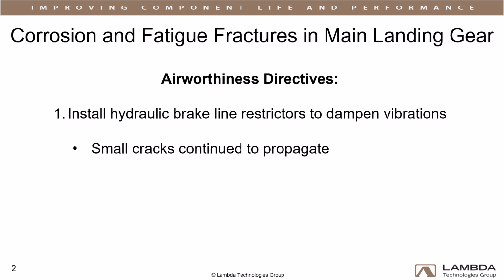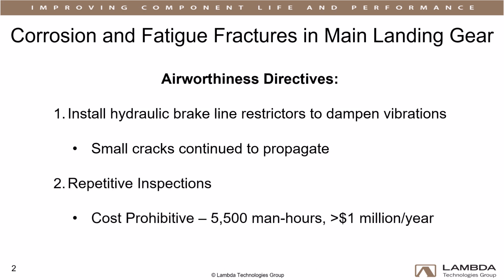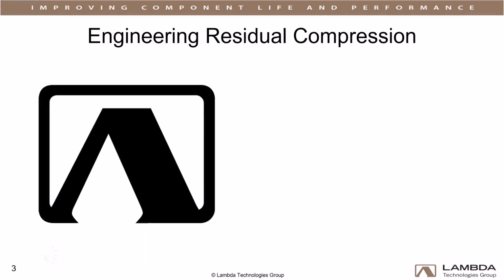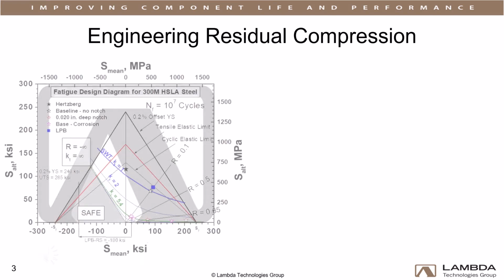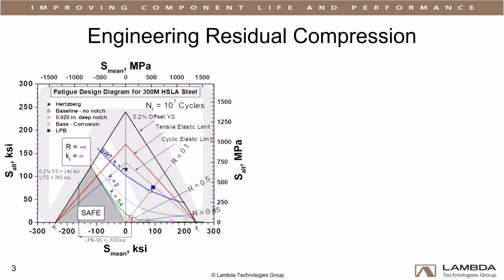A subsequent directive mandated repetitive inspections, costing one airline 5,500 man-hours and over $1 million annually, not including losses from downtime. Replacing each cylinder, priced at $80,000, seemed to be the only solution to curb inspection expenses. The company began to explore other options. At Lambda, our primary approach to component enhancement and crack mitigation is through the introduction of designed or engineered residual compression. This proved to be a much more cost-effective solution to the MD-88 landing gear concerns.